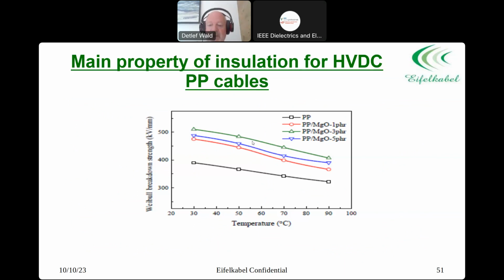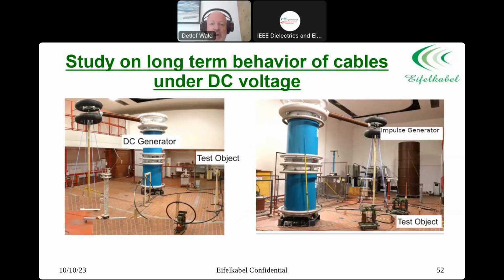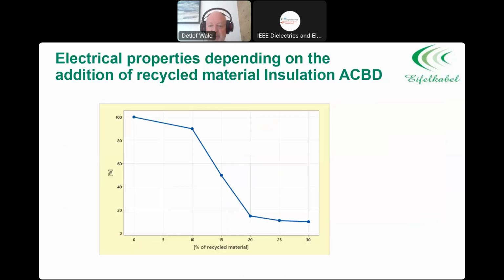I must say there was more focus on magnesium oxide because there are commercial XLPE formulations that are installed using magnesium oxide as a space charge reducing or HVDC additive. Showing you a little bit, the studies were done at the University of Graz, and they were presented at the Jicable, where the DC cables were tested over a longer time under DC voltage, making actually a faster PQ test that was described in the CIGRE TB 496, and showing that you can use these cables perfectly for these applications.